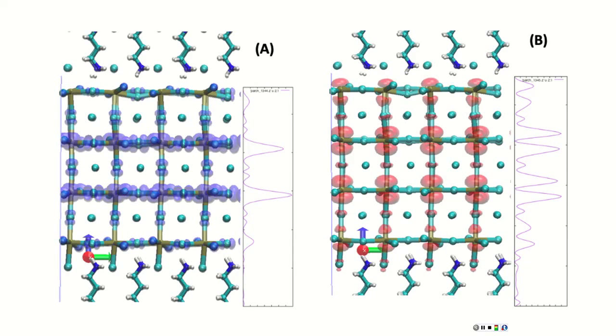Yeah. Because this is a three-dimensional structure. This is a two-dimensional. Yeah, this is a three-dimensional structure. Thin film has two-dimensional features, but it is represented periodically. But anyway, here the surface is completely isolated by these ligands, right? And they do not contribute to your HOMO-LUMO gap, while the other one has these orbitals at top and bottom completely occupied, and this probably caused this difference in the band gap, right? So the organic layer works as an insulator, and the inorganic does not.